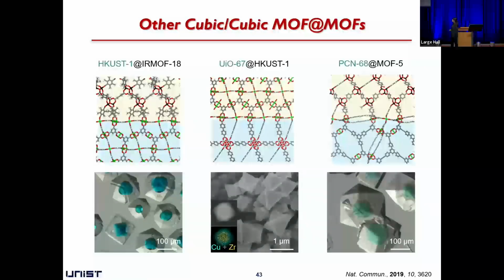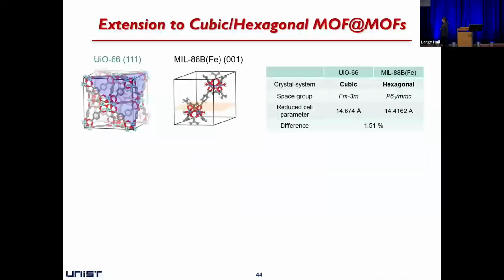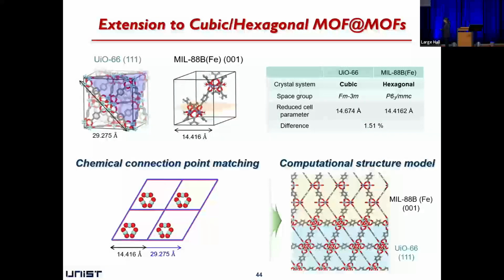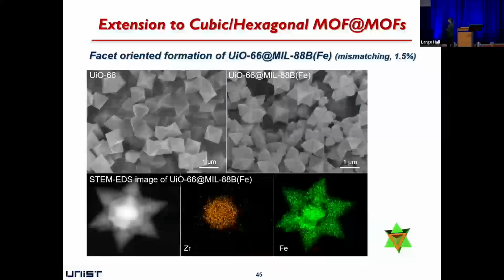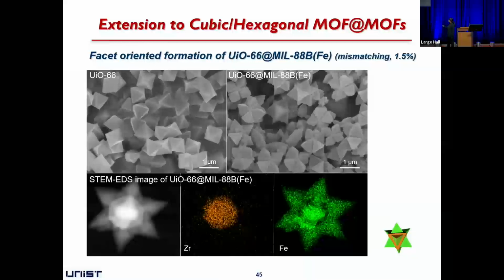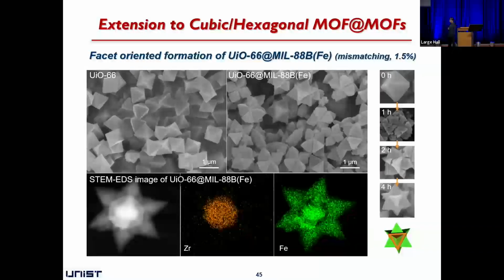We can extend this experiment to other pairs of a cubic system: HKUST-1 at IRMOF-18, UiO-67 at HKUST-1, PCN68 at MOF5. We also can extend this experiment to a cubic hexagonal MOF-on-MOF system. For example, UIO66 and MIL88B. Okay. Actually, if you consider the reduced cell parameter, it showed quite a good lattice mismatching, right? And by considering the chemical connection point matching as well, oh, we can try this pair as well. The result is like this. On the surface of octahedron UIO66, you can see the growth of a MIL88B crystal, and we can see the star-shaped core shell structure.